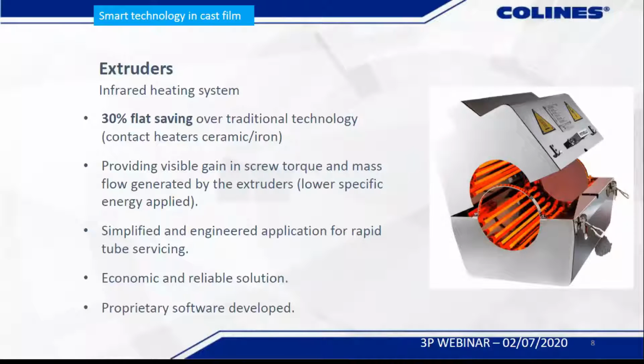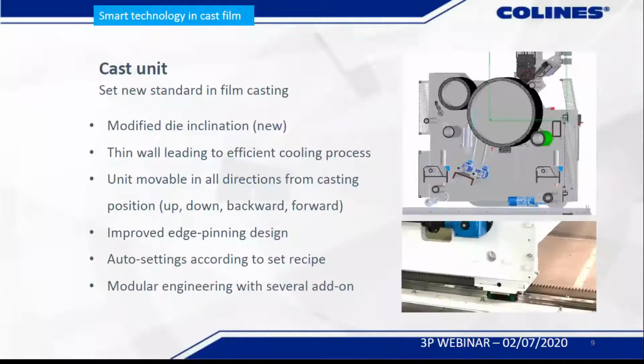In terms of the casting unit, we have a new layout of the machines that sees a new inclination of the die. We have even further improved the wall, making the cooling process more efficient. And now the unit can be moved within linear guide. So up, down, backward, forward, but not anymore on wheels, but on linear guide, providing a much better control over vibration at very high speed. We also went to 1,000 meters per minute with machines for stretch film with this kind of design. And basically it also makes easier the way the recipe is set on the machine.